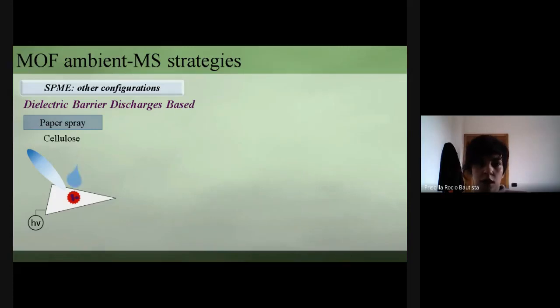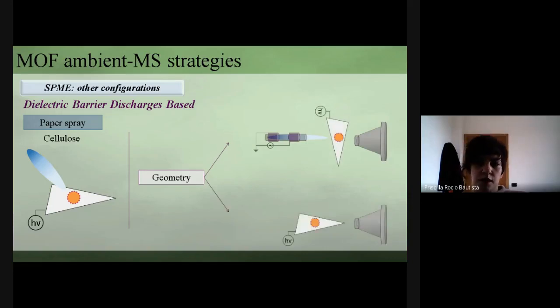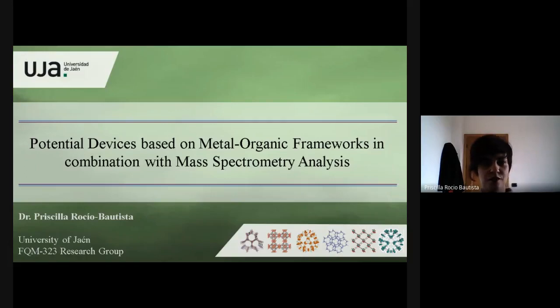Then we can use a solvent as cleanup in order to reduce matrix effect. And finally, as with the blade coating, the paper spray is combined with the plasma to favor the ionization. Geometry can be a crucial parameter in the desorption step. Therefore, we will study different configurations between plasma, device, and MS. And of course, the geometry will be studied not only in paper spray, but also in the previous configuration with the blade spray. Thank you for your attention.